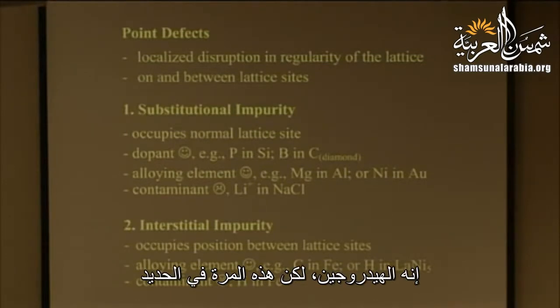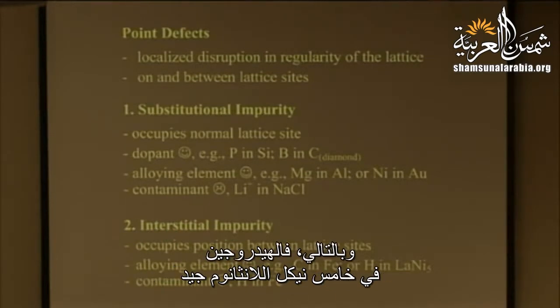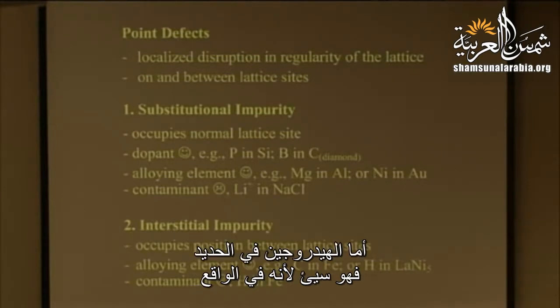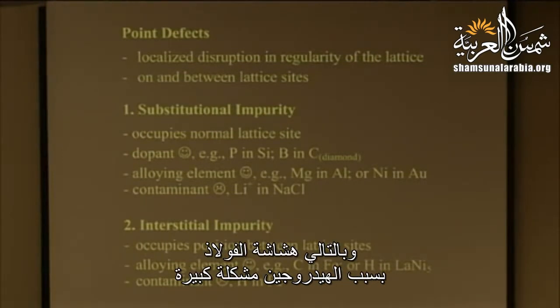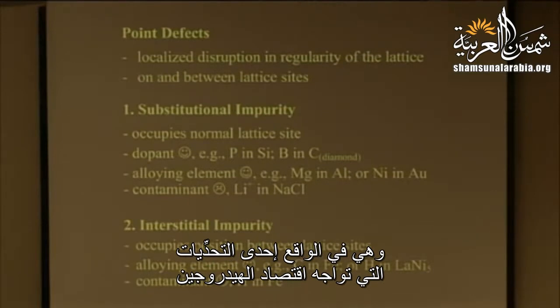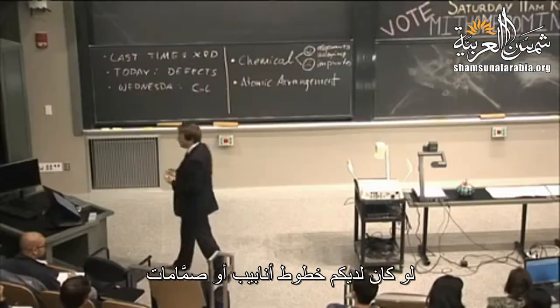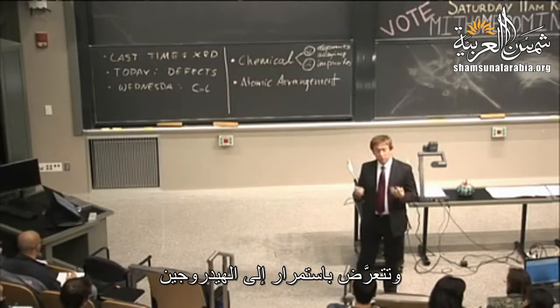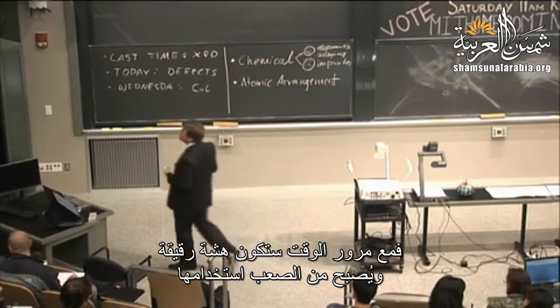Here's another example of an interstitial impurity. This one is not an alloying element, it's a contaminant. So hydrogen, but this time in iron, right? So hydrogen in lanthanum nickel 5 is good, we want to store it. Hydrogen in iron is bad because it actually degrades the mechanical properties of the iron. Unlike carbon, which gives us steel, which is good, if you put hydrogen in, it embrittles it. So hydrogen embrittlement in steels is a big problem. And it's actually one of the challenges to a hydrogen economy, right? If you have steel pipelines or valves or various pieces of machinery, structural components that are made out of iron, and they're constantly exposed to hydrogen, over time they're going to embrittle. They're going to become very difficult to use.